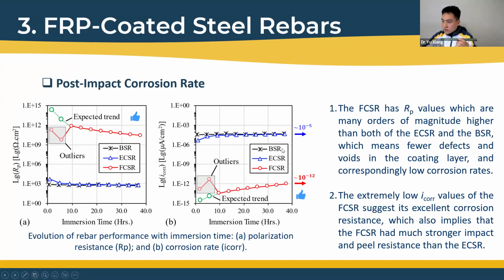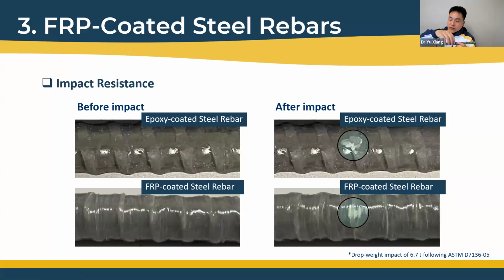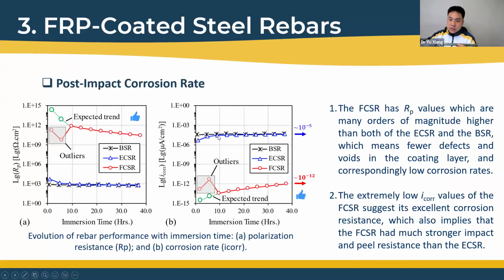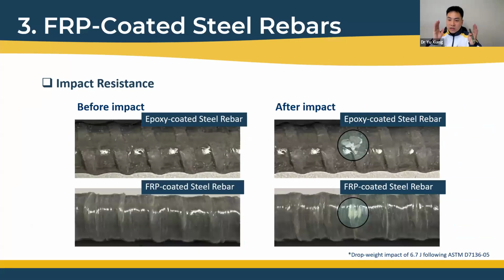So for this test, we first apply an impact to destroy the coating layer, simulating possible collision or impact during operation or construction. Then we do the electrochemical measurement, and in that way we can measure the corrosion rate. You may ask how to compare if all these rebars were in a very good state—that is very difficult. But the actual situation in our on-site construction is that epoxy coated steel rebar indeed has many defects on the coating layer, so we think the measurement can reflect the real situation.